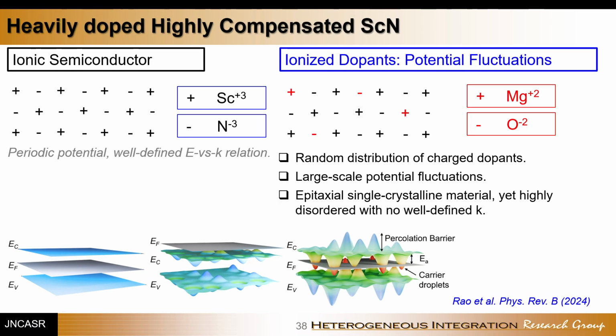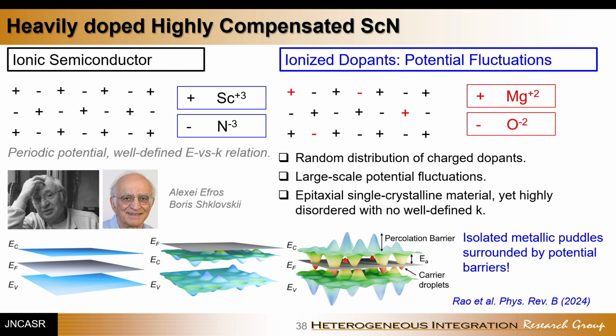And this is basically shown in this particular way. This is the real space diagram of the conduction band and valence band. As you can see, the fluctuating potential basically changes the edges of the band. In some regions, you have the conduction band underneath the Fermi energy. In some regions, the conduction band is over the Fermi energy. And there is a barrier which is known as the percolation barrier. So if you consider it as a simple picture, this highly doped, heavily compensated semiconductor acts as if it's a dielectric material with different metallic bubbles embedded in a dielectric host. And theoretically, it was shown some time back by Efros and Shklovskii.